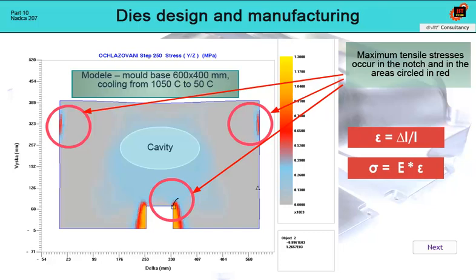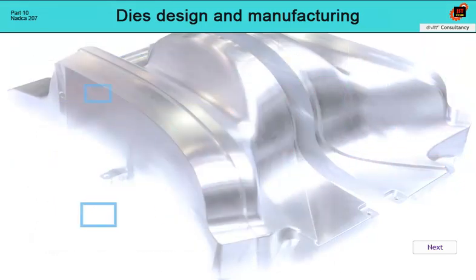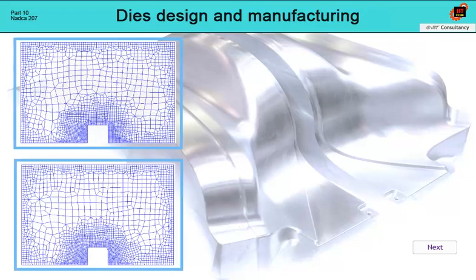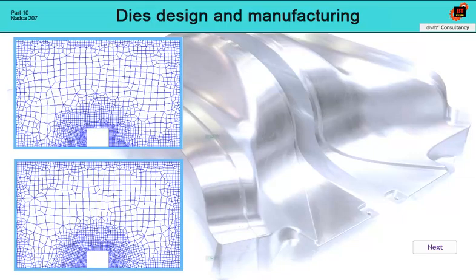This is very important because the designer concentrates on getting the cavity shape into the die correctly, and the auxiliary shapes on the periphery are usually no longer important to him. On the stress model, the stresses in the notch area were compared when the notch is made without a radius, and when the radius was 10 millimeters. The image raster represents the computational network.